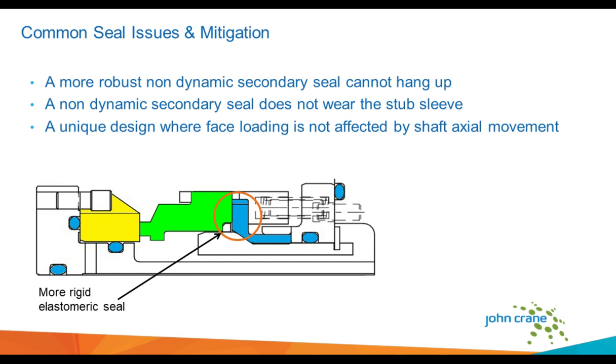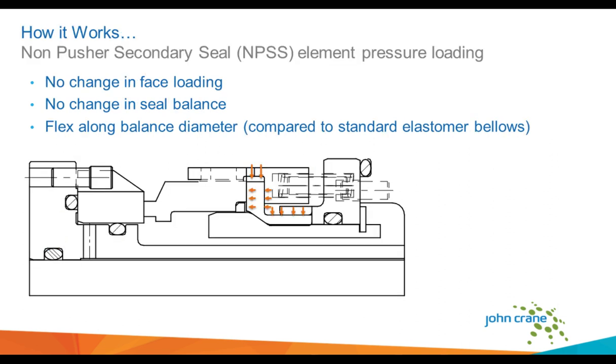When you look at this elastomer sealing element, if it was a full convolution bellows, which has been out for 60 years, that full convolution bellows will collapse under pressure. That collapse causes a change in the pressure percentage acting on the faces. In this case, there's no change in that face loading. The percent of face loading stays the same. The component itself will shuttle and move with the shaft. And we have seen applications as high as 10 or 15 thousandths of an inch, and we've actually designed it to handle 31 thousandths of an inch in each direction.